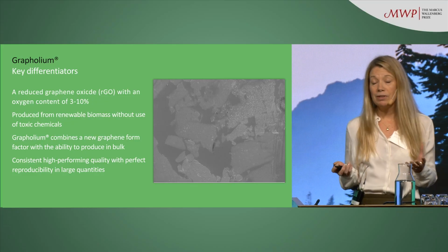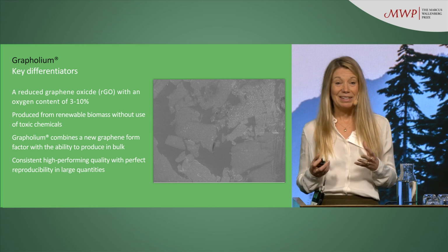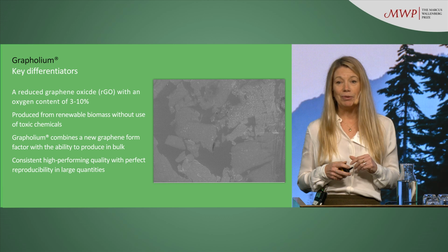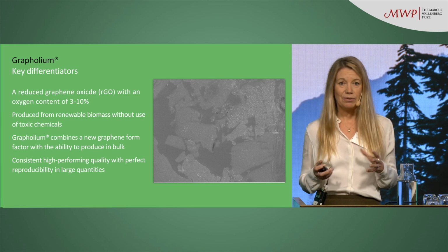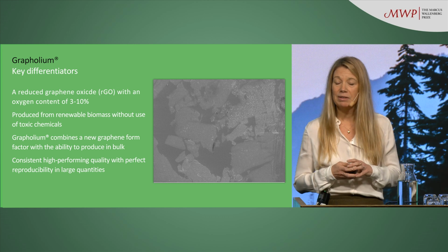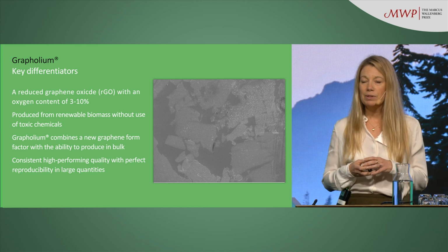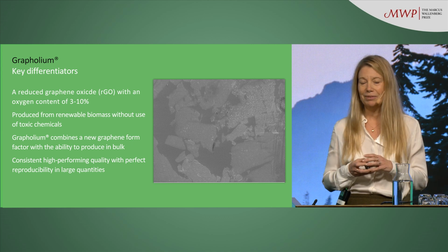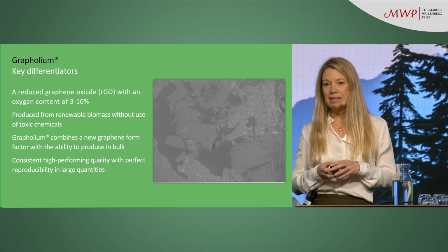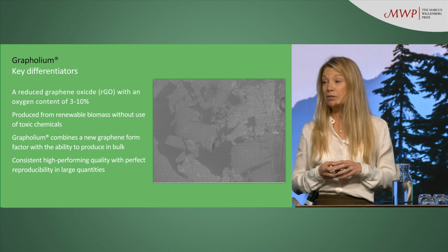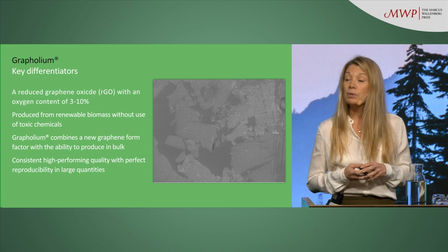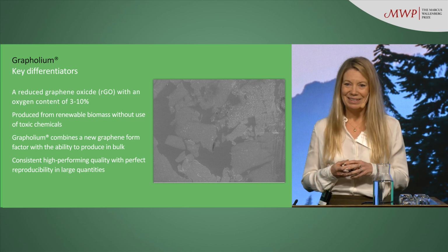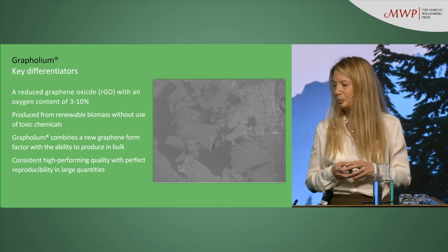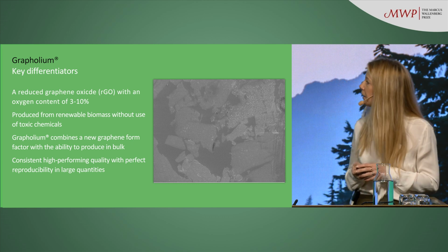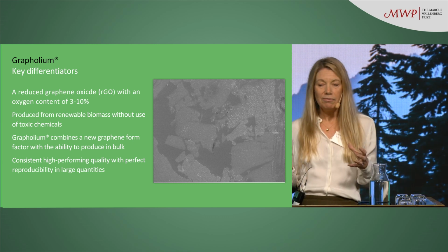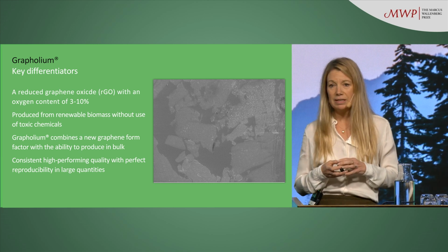And the most important feature for us with our graphene is that we call it green, because it's from a renewable source, instead of a finite resource, as most graphene comes from graphite. And graphite is also, since 2020, on the EU list of critical raw materials, because we use a lot of graphite in Europe today, and we need to import 95% of it, mostly from China. So to be a more resilient society, it's good if we can move away a little bit from graphite or find other sources to make it. And then we have these large thin flakes that we get that gives us a lot of good properties.